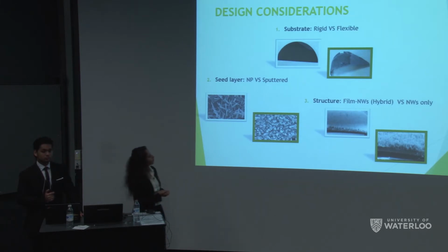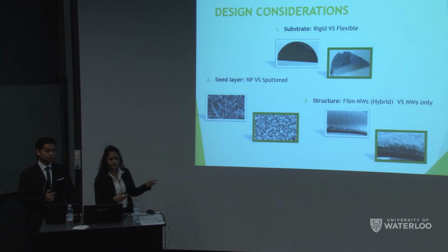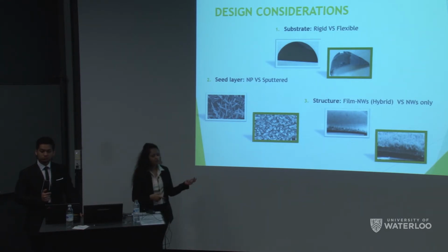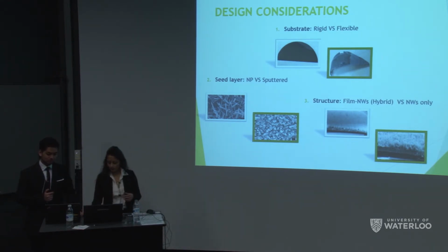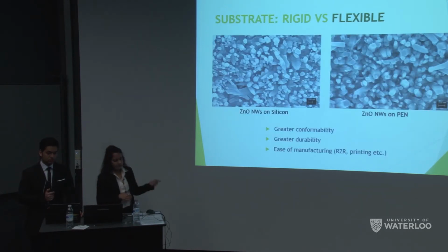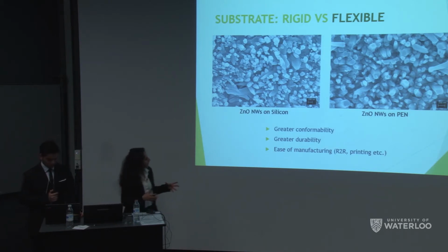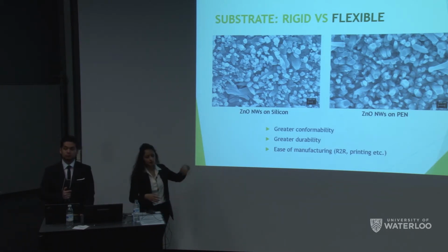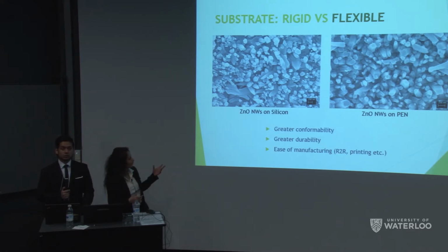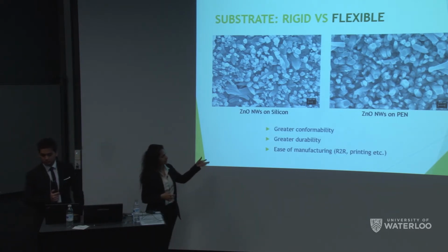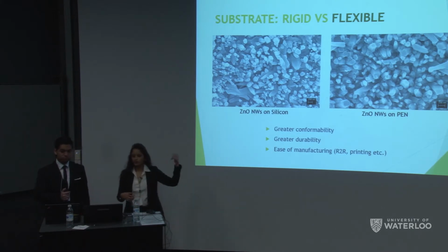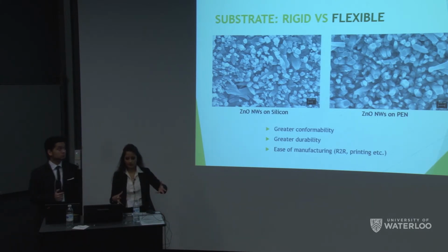So as I'd mentioned, we considered a lot of different factors to reach our final device. And the three main factors that we considered were substrate, which seed layer to use for the growth mechanism, and the final structure, the piezoelectric element of the device. So the substrate, we were debating between whether we wanted to go rigid or flexible. And so we went ahead and we tried on silicon and glass as well as PEN, and we grew some nanowires. So the images here show that in terms of the growth, we got pretty uniform and pretty similar growths on both the substrates.